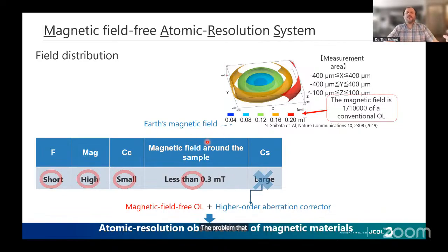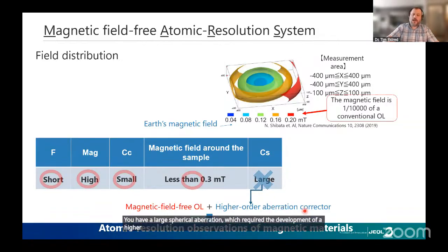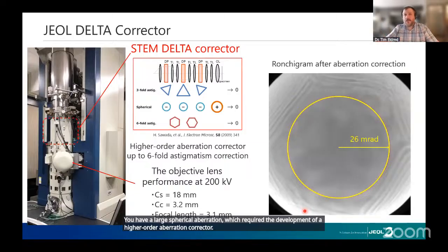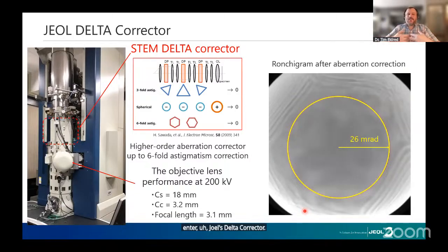The problem that an approach like this has traditionally led to is you have a large spherical aberration, which required the development of a higher order aberration corrector. Enter JEOL's delta corrector. This is a triple dodecapole corrector. Instead of worrying about the specific lensing on it, what we need to focus on is this unlocks aberration correction up to 5-fold, which allows 6-fold astigmatism. And so even in this system where now we have separation of our objective lens, we're still able to get these extraordinarily good ronchograms that are large enough for us to do atomic resolution work.